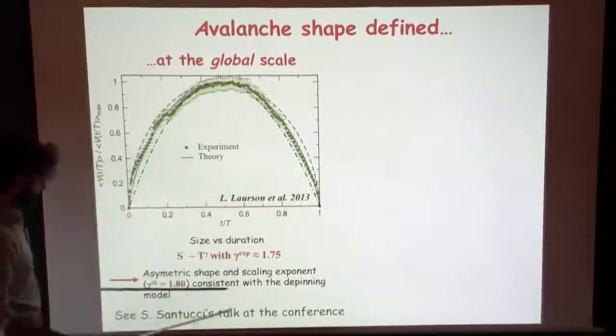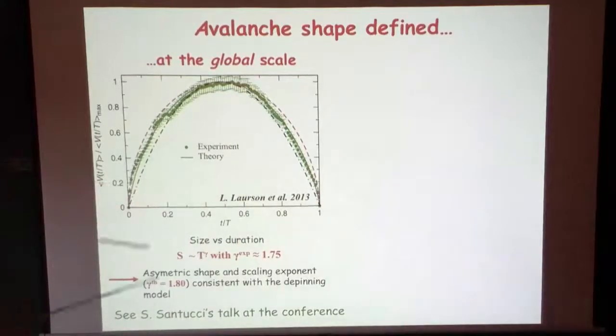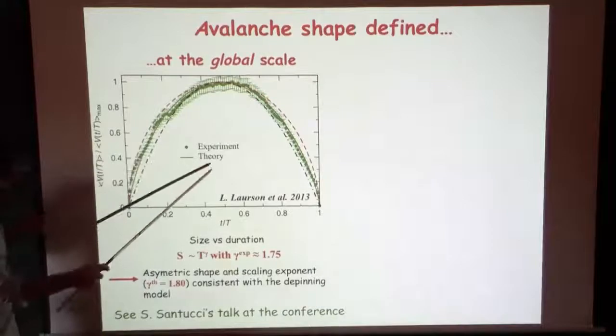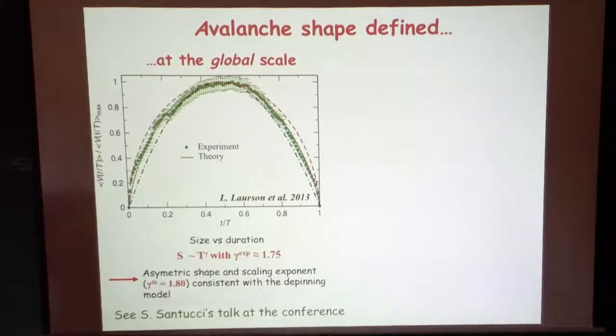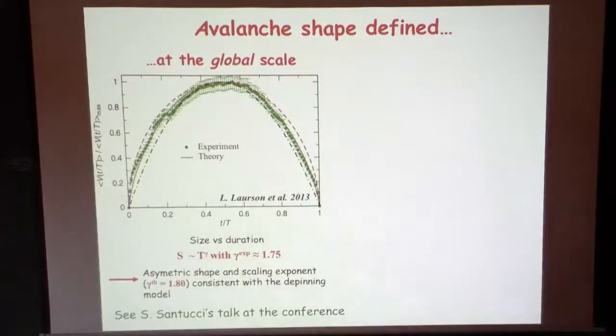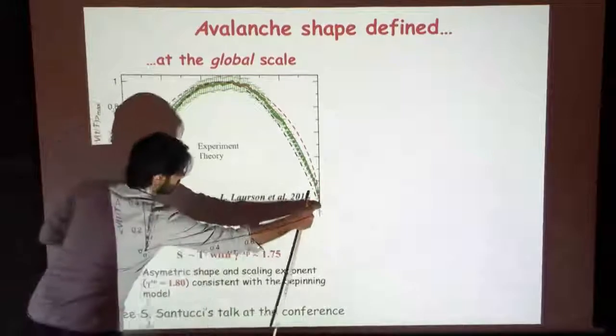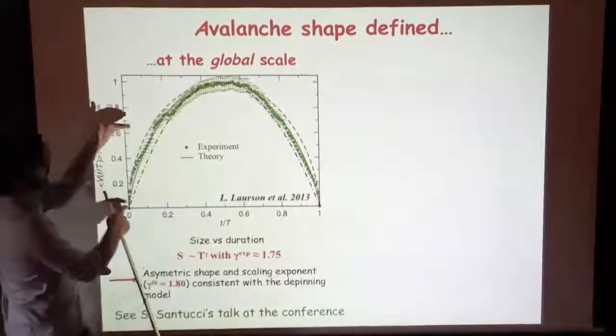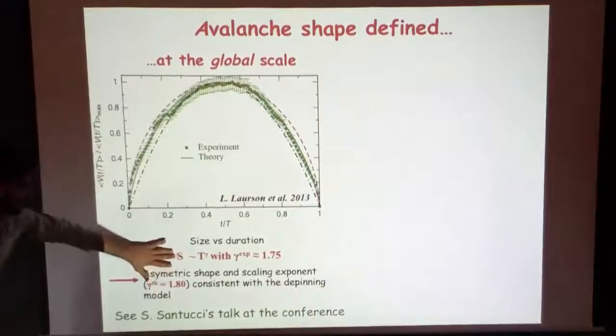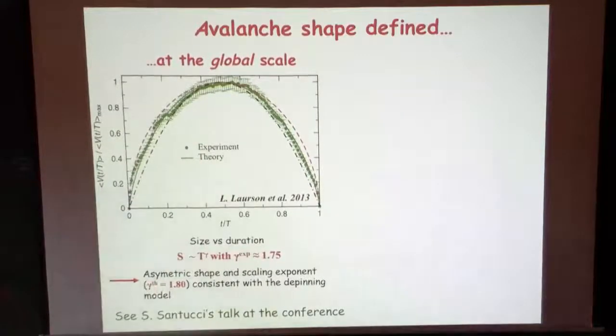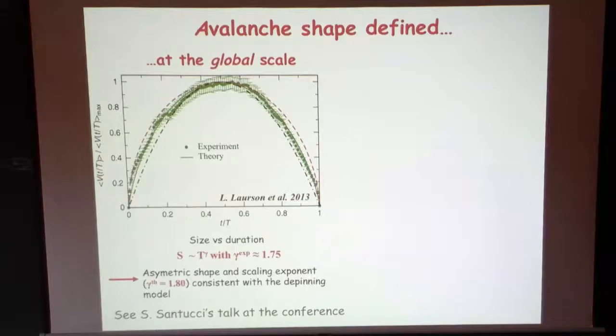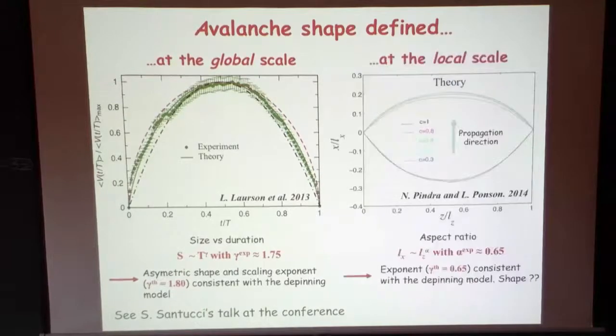And in this work with Laurson, Mikko Alava, and co-workers, they compare with the theoretical model with the long-range elasticity, and they found a reasonable agreement. The red and the black are other models, short-range or other kinds of elasticity. Interestingly, they also found a scaling between the duration of the avalanche versus the size, the energy of one avalanche, with an exponent close to the one predicted by the depinning model. So at the global scale, the avalanche shape seems to give a closer result than the statistics of avalanche size for the depinning model.